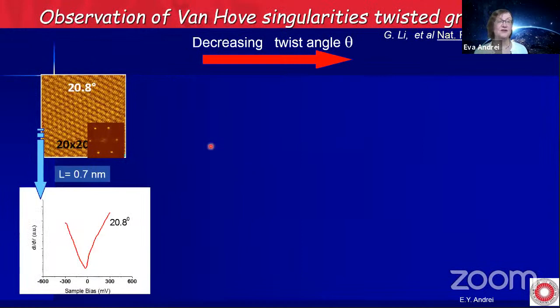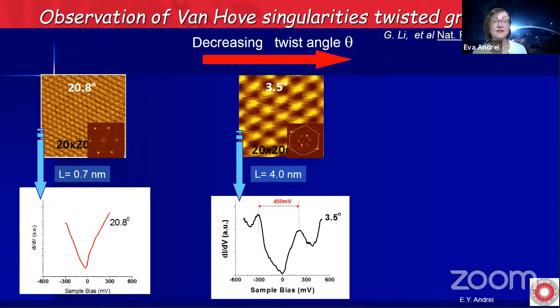So here's what we saw. Here we have graphene layers with a twist angle of 20 degrees. The density of states looks more or less like that of single layer graphene. It's kind of V-shaped with a minimum at the Dirac point. The angle, of course, we know by measuring this period here. We can also measure it from the Fourier transform of the period. Now we go to a smaller angle. This one is now 3.5 degrees. Now you see these peaks started appearing. The density of states is now no longer the same as that of single layer graphene.